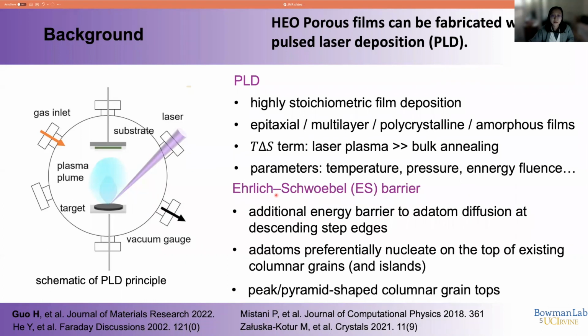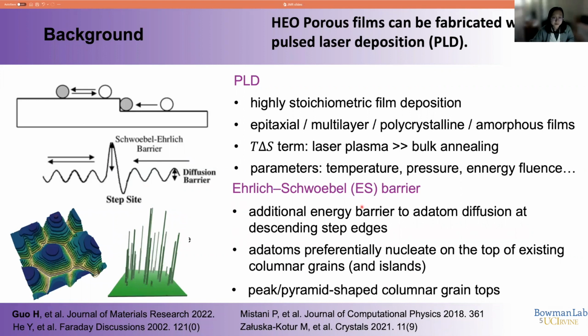So next, what about growing the porous films? I want to introduce this concept, the ES barrier. That means there is an additional energy barrier to atom diffusion at the descending steps of edges. That means the atoms prefer to be deposited on the top part of the grains instead of the edges of the grains, because they have the ES barrier here to impede atom diffusion. So using this principle, we can make the porous films by controlling the energy barrier as well as the kinetic energy of the atoms.